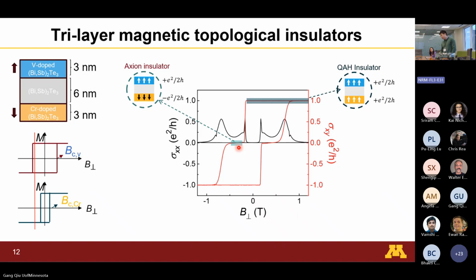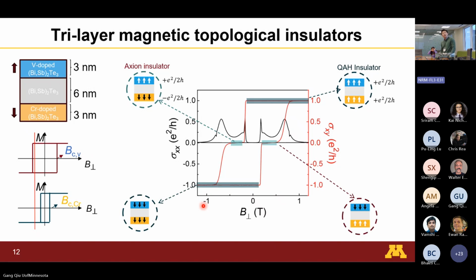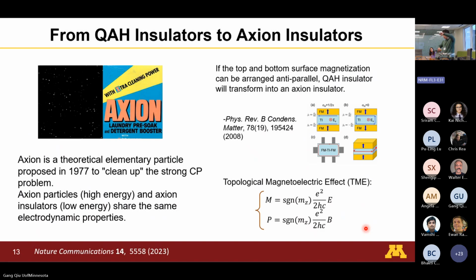And I have a very brief introduction to this in the next slide. But for now, we just keep scanning the magnetic field this way, right? You can imagine if you keep going in this direction, both of them will be pinned downwards. And you enter this quantum anomalous Hall state again, and then you go up this way. The chromium will flip first, and then you enter the axion insulator state again. All right. So that's pretty cool, right? But the result seems quite straightforward, right? So it turns out that middle state where you have this anti-parallel state is something very significant.